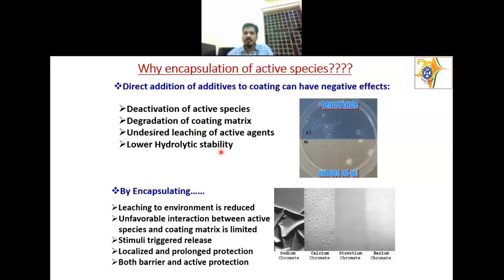So sometimes undesired leaching of these inhibitors will be there. In order to avoid that, what we can do is load these inhibitors inside some containers or some reservoirs and add them here. So by encapsulating, the leaching to the environment is reduced, unwanted leaching is not there, and there is no unfavorable interaction between the active species and the coating matrix. You will have a stimuli-triggered release as and when required only, and localized release will be there, and prolonged protection will be there because there is no unwanted leaching and no deactivation of the active species, and it can have both the active and barrier protection.